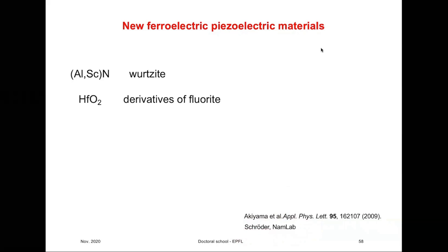Being ferroelectric, that material is also piezoelectric, and I think this group is also testing hafnium oxide and its derivatives for piezoelectric applications, for energy harvesting, pyroelectricity, and so on. The advantage would be that it is lead-free. Hafnium oxide is a known material in the semiconductor industry as a high-k, high dielectric permittivity material.